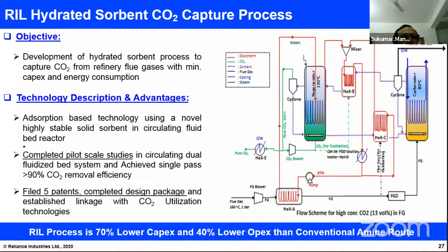So this process is an adsorption based technology using a novel, highly stable solid sorbent in a circulating fluid bed reactor. We have completed pilot plant studies in a circulating fluid dual bed system and achieved single pass more than 90% CO2 removal efficiency. And we filed five patents, and some of them are already granted, and completed the design package, and then established the linkage with CO2 utilization technology. So the capex cost is much lower, 70% lower capex, 40% lower opex than the conventional route.